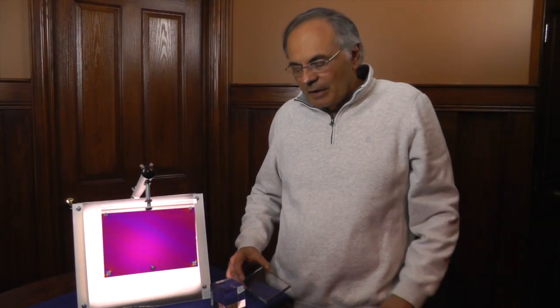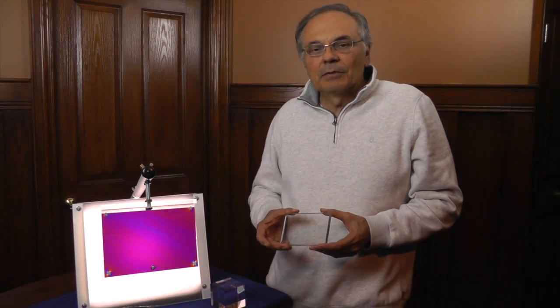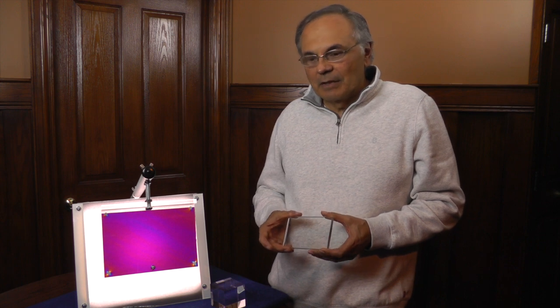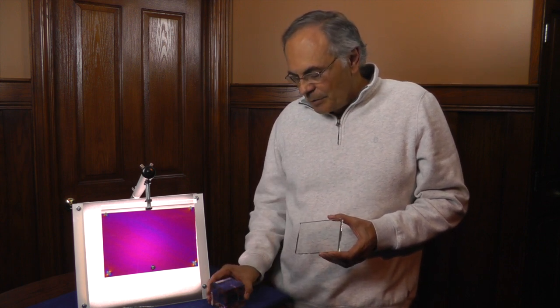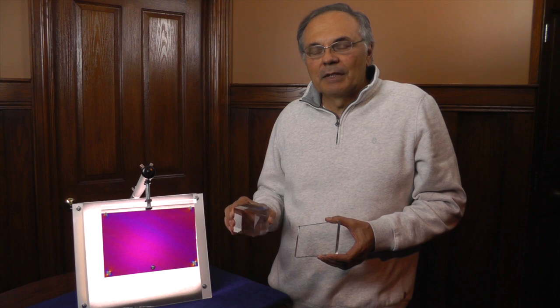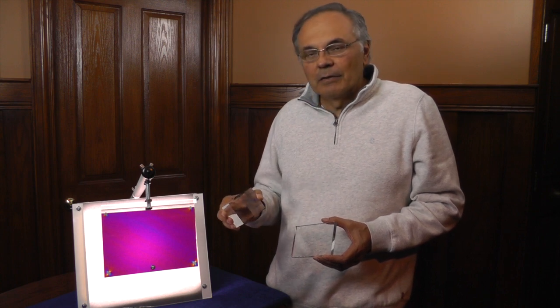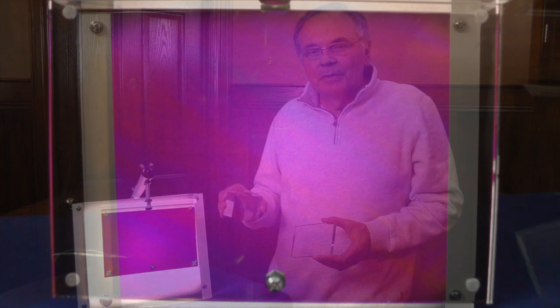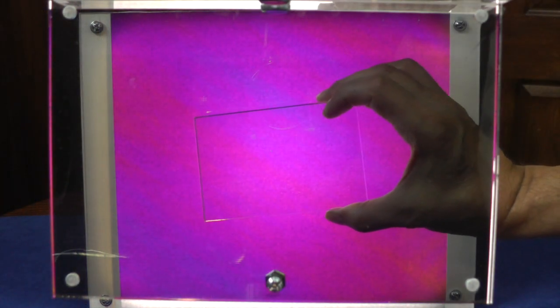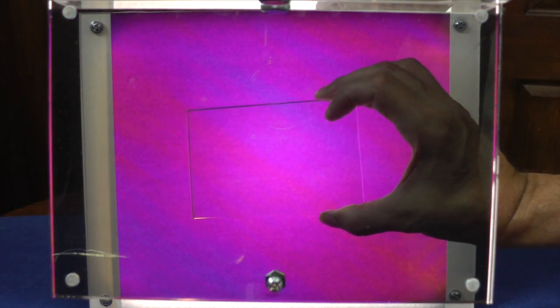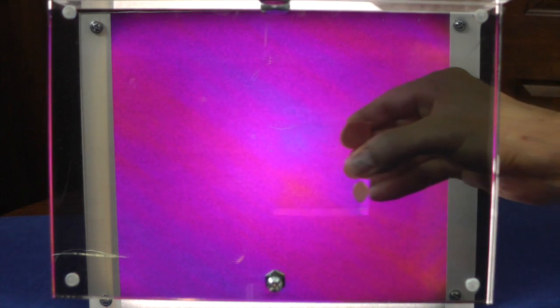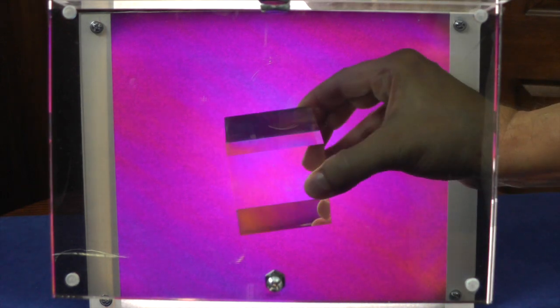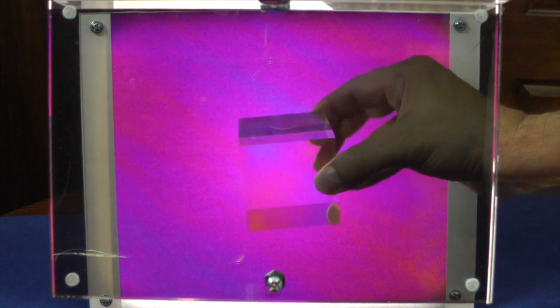In this segment, we're going to take a look at a piece of float glass, window glass, and see what that looks like in the Polariscope. And also a piece of optical glass that's finely annealed that I cut and ground and polished into this cube. You can see in this example of float glass that there is no strain, the light passes right through it. Also with this optical glass, this is fine annealed. Again, there's no strain in it. This is typical of optical glass that's used to be ground and polished into lenses.